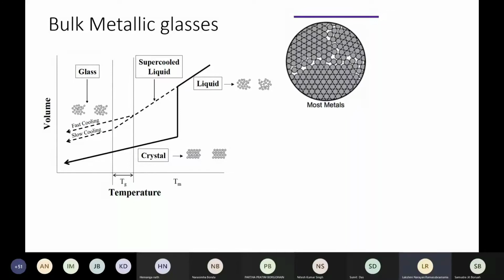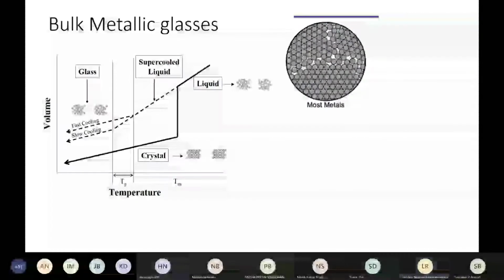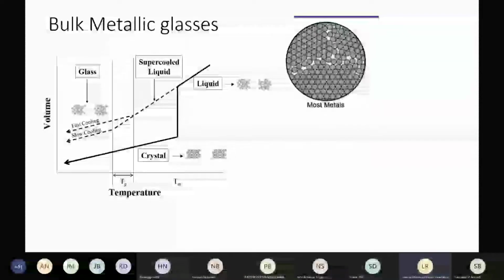And then when you look at the micrograph, when you look at this material under the microscope, for most metals which have crystallized, you will see something like this. Of course, you're not going to see balls. What you're going to see is pockets, and each of these pockets represents a grain. There is one pocket which has a certain orientation of these atoms. That is your grain one, and the others have different orientations, and they are separated by something called a grain boundary.